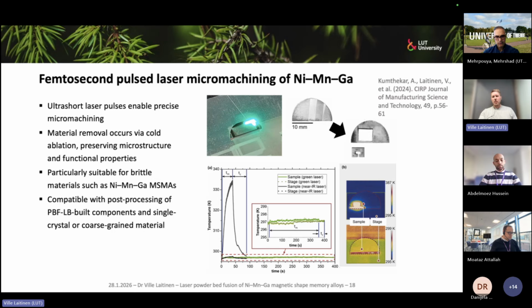So we have an example here where we made, from a single crystal, this kind of micro gripper actuator, and it works fantastically. We have also shown that if we use green light for the machining itself, we actually get a little bit better machining performance, and through this process we can machine it in martensite, so we don't need to heat it to austenite for the machining process itself.